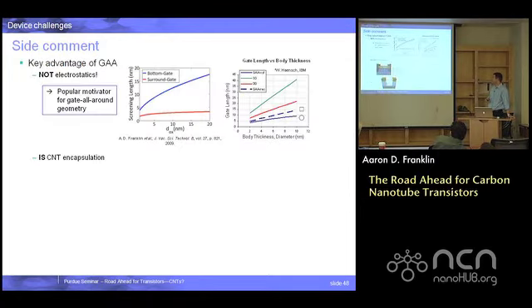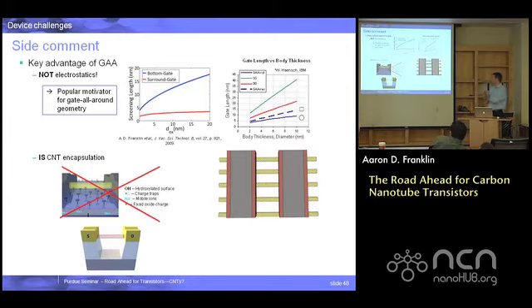This is a comment that I like to make sure and make, and that is regarding why gate-all-around, because it's easy for me to tell you, as I did for many years. This is actually a plot from a paper that I worked on with Tim Fisher here, that I like because we were working a lot on these gate-all-around, surround gate, and back then I motivated it almost predominantly for the electrostatics, because it's the best electrostatics. But the fact is, it's not entirely fair for nanotubes. They are only 1 nanometer. Making a single gate below it is plenty of amazing electrostatics for making a sub-10 nanometer channel. And we showed that with the sub-10 nanometer device we made with a cylinder on plate type of a gate geometry.